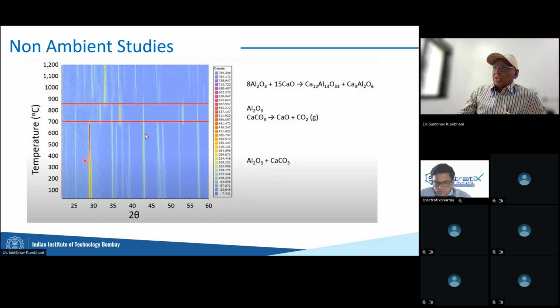So this is what we call a heat map, or 2D XRD data. The way you read a 2D map is true for any 2D map. Any heat map you see in future, you can read it like this. Essentially, this 2D map was created by measuring an entire 2 theta range, like we did with the moving of X-rays that covers this entire 2 theta range. They measure it at one temperature, and one dot will come on the entire plot here. Then another spectrum is taken, which is superimposed over here. Then another spectrum is taken, which is superimposed over here. If you keep doing that for hundreds of temperatures, and then zoom out a little and look from the top, all you see is just lines created like this.